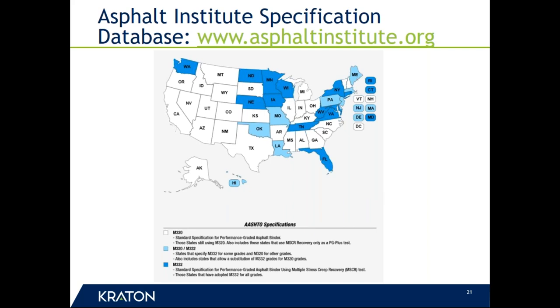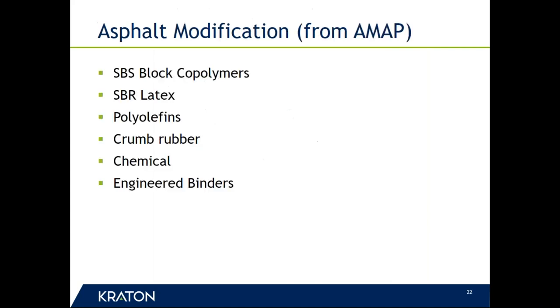And my opinion on this is that this is beneficial to the industry. I can tell you this, having worked for a binder supplier where we had a laboratory and were doing testing, we greatly preferred doing the MSCR recovery rather than having the ductility bath, having to stretch the specimen and do all those sorts of things. That was a pain in the backside. And so we were definitely in favor of doing that. It was just much more practical. And as it turns out, from the research that we've seen, it seems to be a more effective way of characterizing modified binders as well.